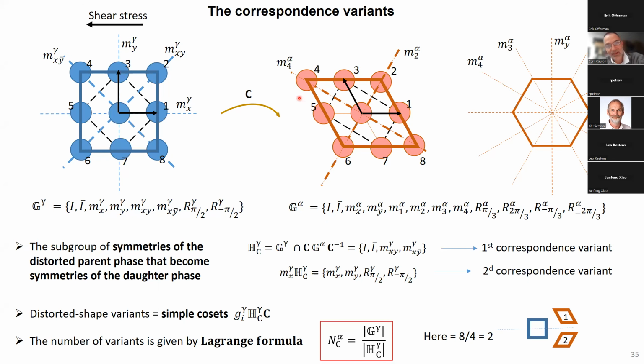I would like to tell you that we can do the same for the correspondence matrix, and it will be a key point of my presentation. Okay, for the correspondence, what is important is that we need to take into account the lattice distortion, the mechanism. For example, before I told you that we have this mirror symmetry here that was parallel to this mirror symmetry here. But if you take into account now the distortion, it does not work anymore, because atoms 3 and 7 that were in mirror position at the beginning are not in mirror position after the distortion. So it means that this symmetry element is not in correspondence with these symmetry elements.